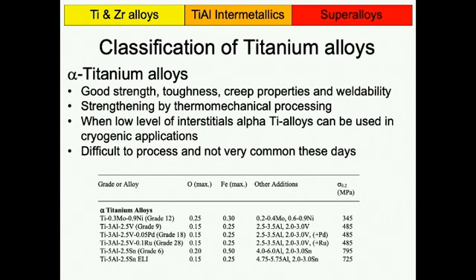So another point here, and I think there's one example here, is if these materials are intended to be used at very low temperatures, so for cryogenic applications. Cryogenic application means you use it at temperatures well below 0 degrees. What is done is that you have an alloy variant which is very low in interstitials. So this ELI means that it's very low in interstitials, so very low in oxygen, nitrogen, all these elements which go interstitial into the lattice. Because they strengthen the material, but they also, especially at low temperature, reduce the ductility of the material. And these alloys are quite difficult to process, and so they are not that common these days.